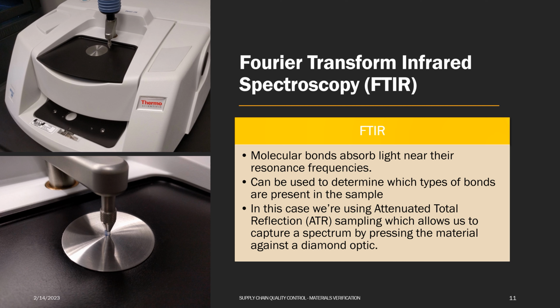The second technique we used to try and determine what this material was and what potential contaminants are present was Fourier transform infrared spectroscopy. Different molecular structures absorb light at different frequencies, and this spectrometer allows you to determine what types of materials are present, what types of functional groups are present, and what types of contaminants are present in a material. In this case, we're using attenuated total reflection, ATR sampling. It's very limited sample prep required, which makes it very quick and easy to run and broadly applicable. You just press your sample against a diamond optic here to obtain your spectrum.